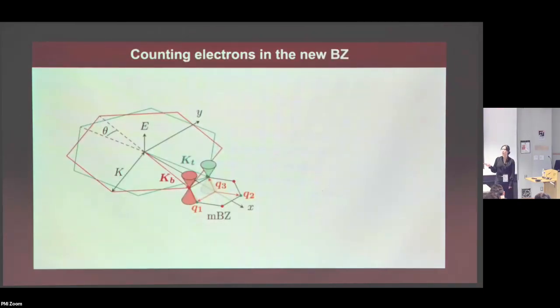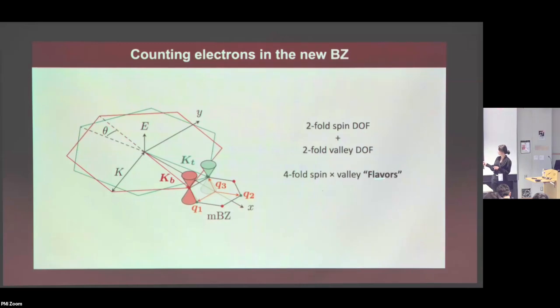And one point that I just want to go over before looking at the actual experimental data is that when we twist these materials, what happens in momentum space is that you fold and form this mini Brillouin zone. And in this mini Brillouin zone, you still have this 2-fold spin degree of freedom and 2-fold valley degree of freedom. Therefore, the total 4-fold spin and valley flavor, or some people call it isospin degree of freedom, inherited from monolayer graphene. Okay, so this means that in real space, you would have 4 electrons or 4 holes per Moiré unit cell to fill each of the flat bands in either direction. So this kind of 4-fold degeneracy is not just for twisted bilayer graphene, but also applicable to twisted multilayer graphene, no matter how many layers you have.